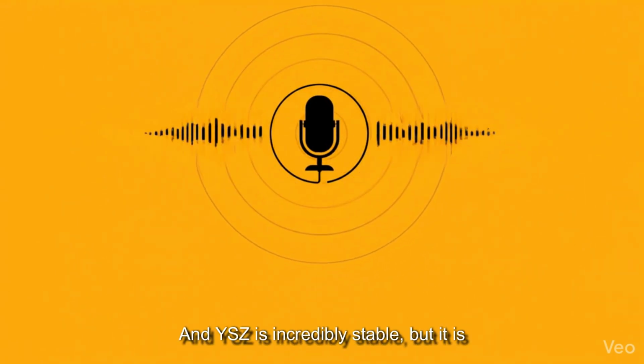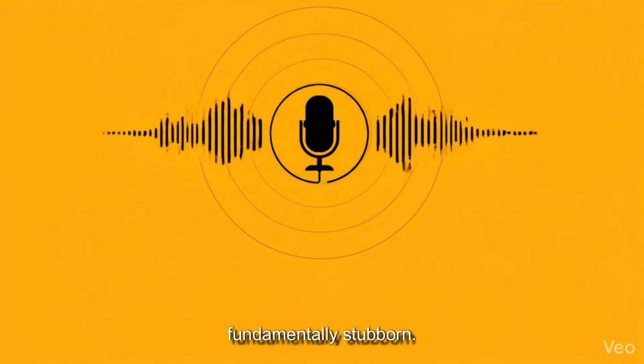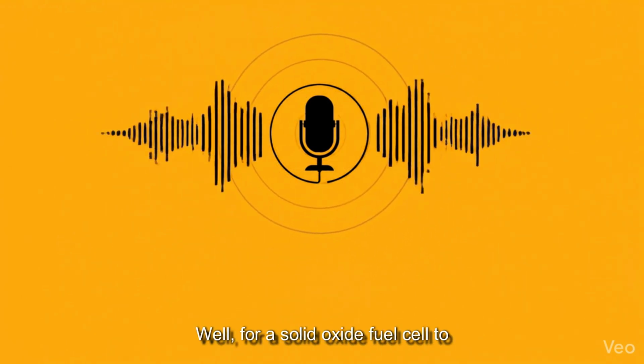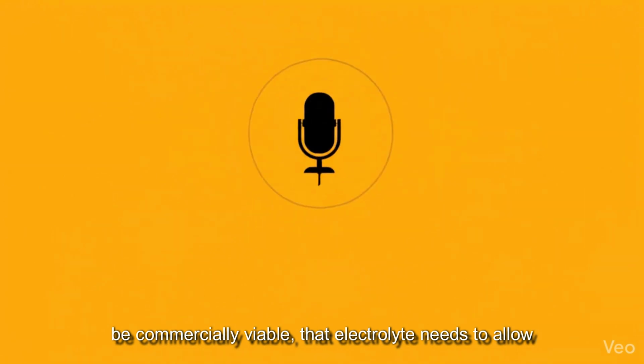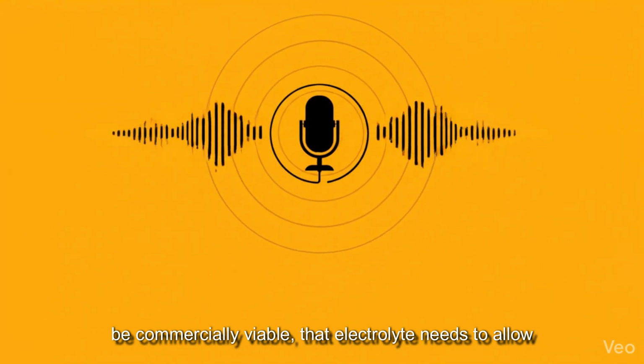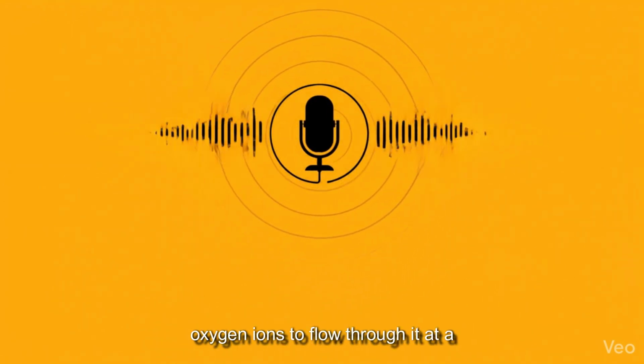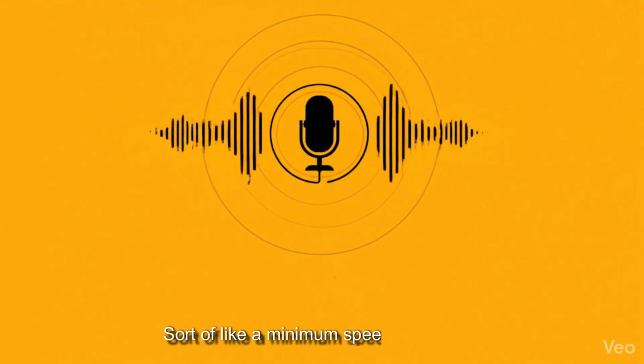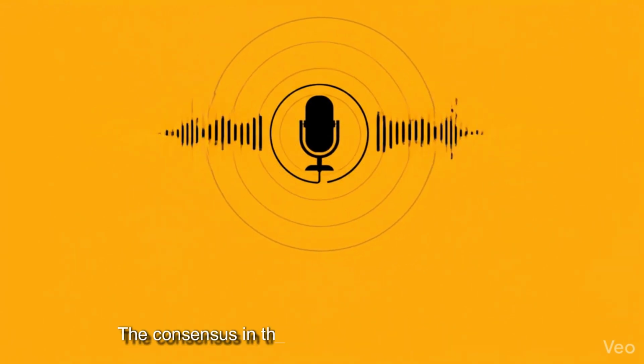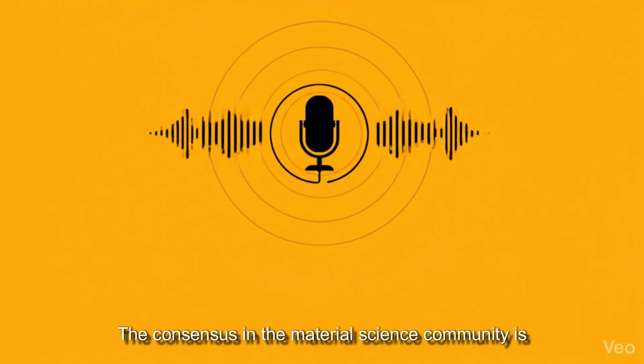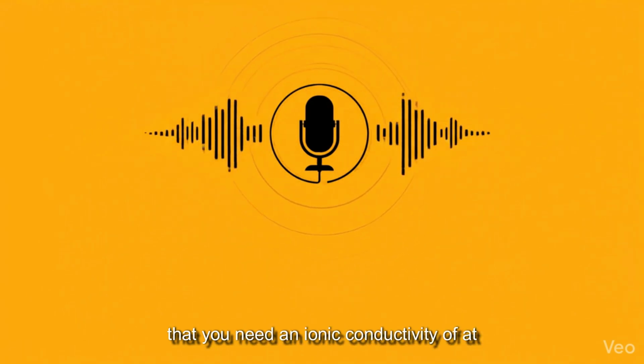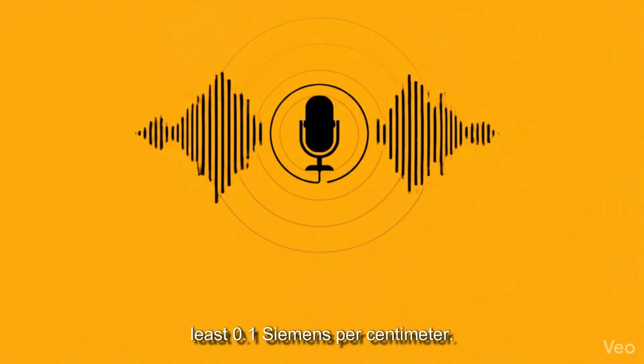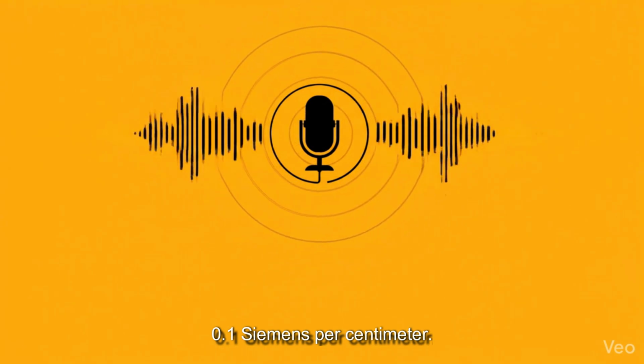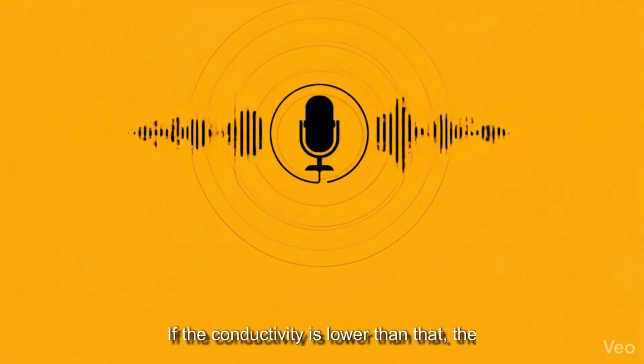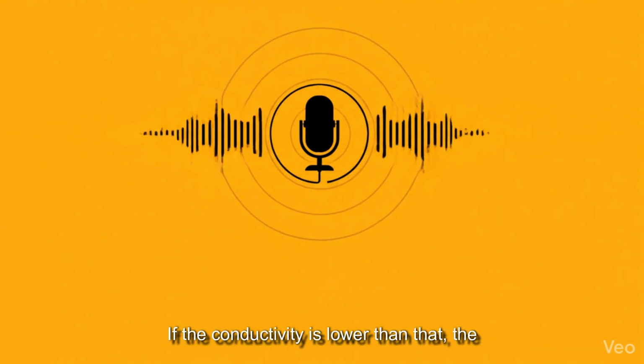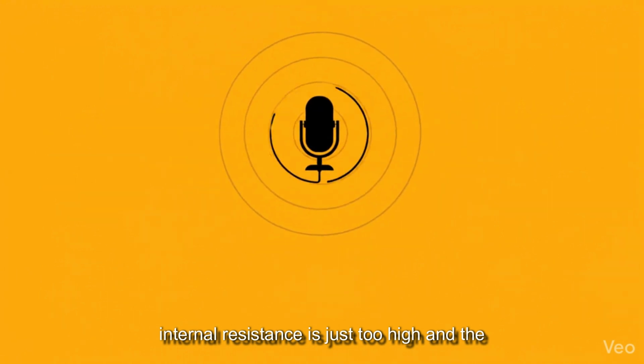YSZ is incredibly stable, but it is fundamentally stubborn. How so? Well, for a solid oxide fuel cell to be commercially viable, that electrolyte needs to allow oxygen ions to flow through it at a very specific rate. Like a speed limit. Sort of like a minimum speed limit, yeah. The consensus in the material science community is that you need an ionic conductivity of at least 0.1 Siemens per centimeter. 0.1 Siemens per centimeter. Got it.